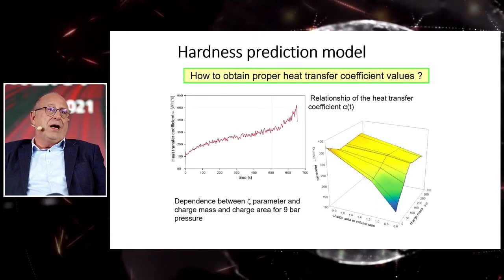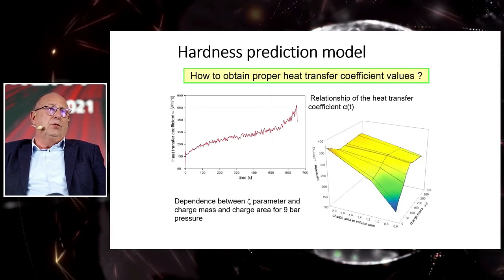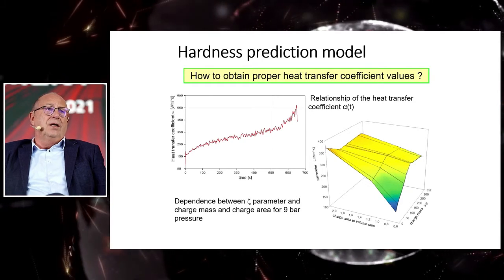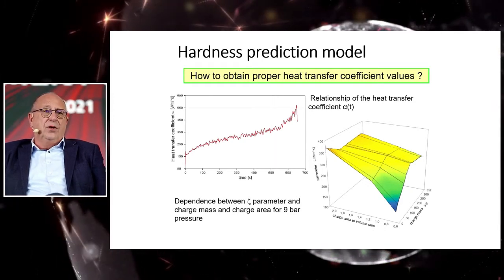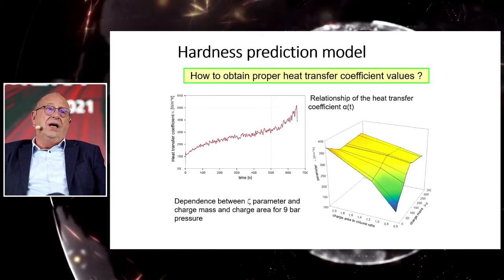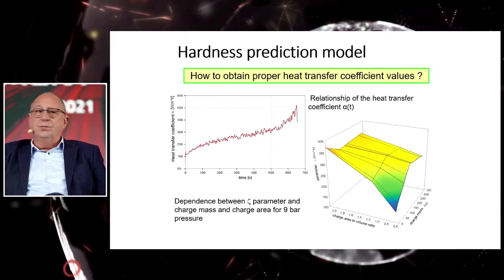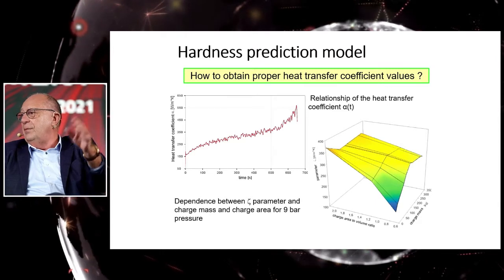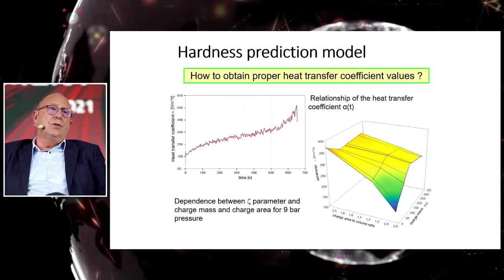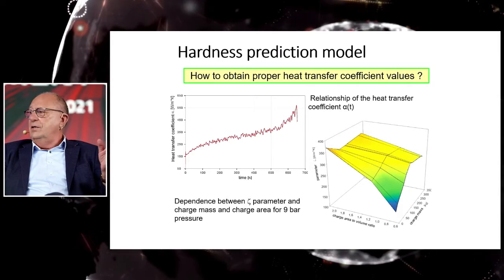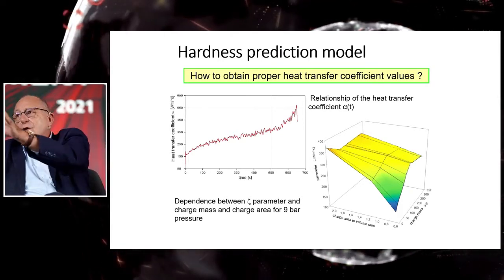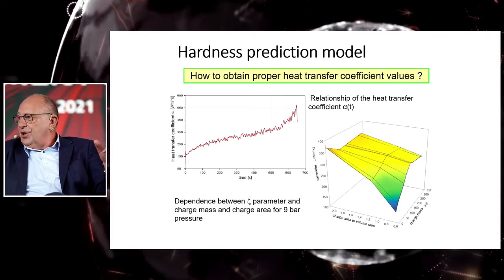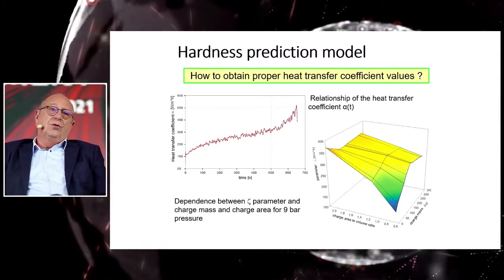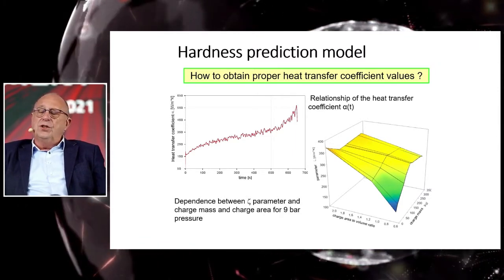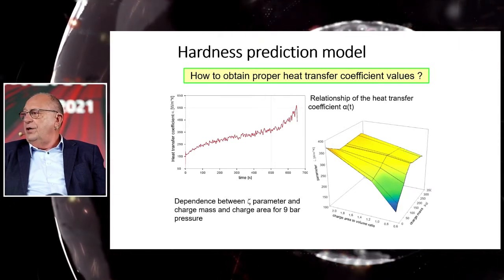So finally, we described the relationships between heat transfer coefficients versus time for the fixed pressure of inert gas, and we introduced into the memory of this program this three-dimensional relationship of average heat transfer coefficient, the mass of charge, and the shape and area of charge, and these two values describe very well the efficiency of heat transfer.